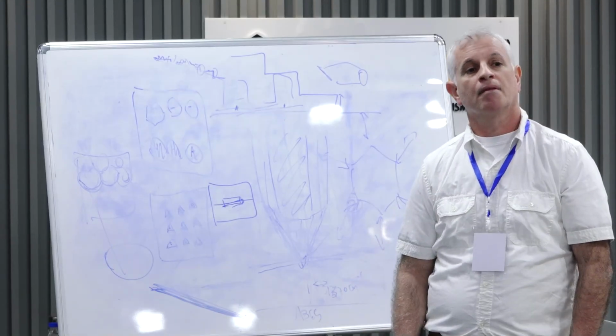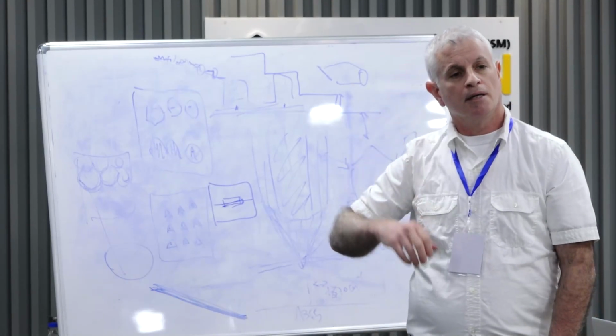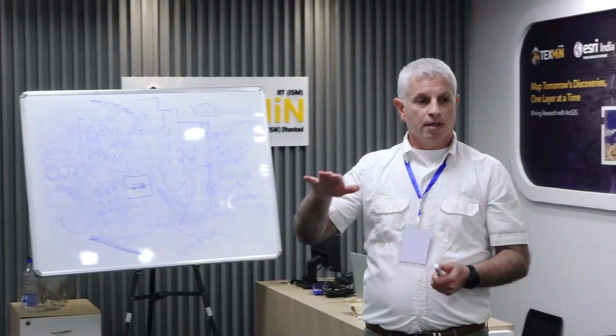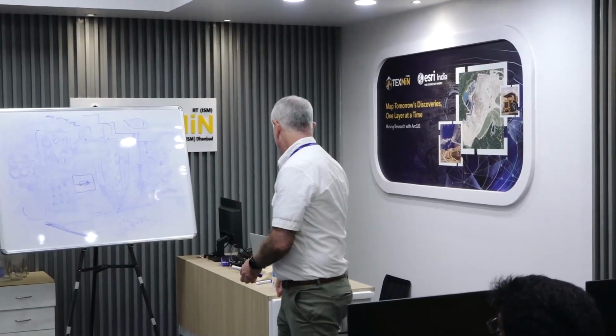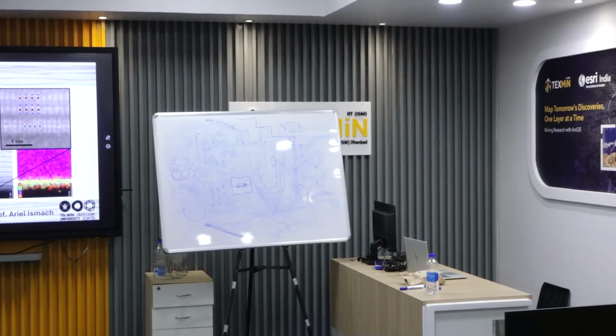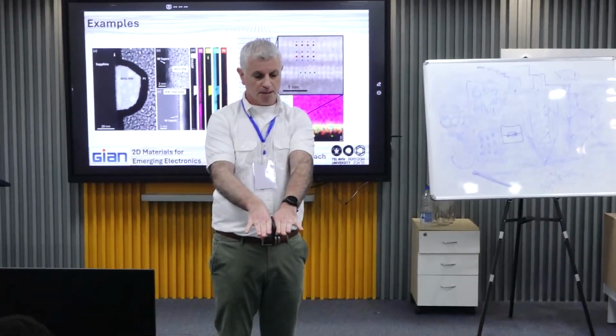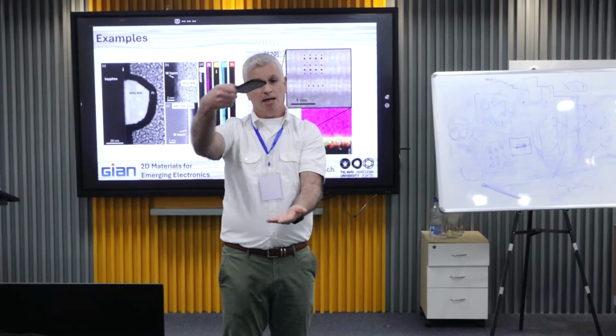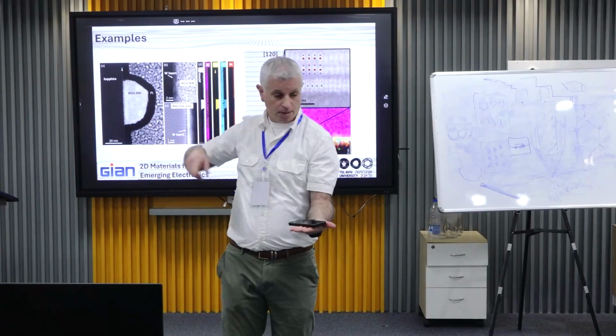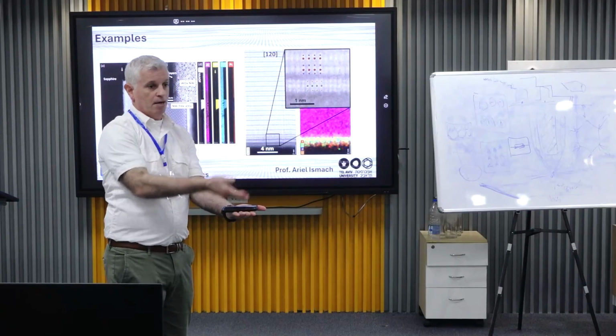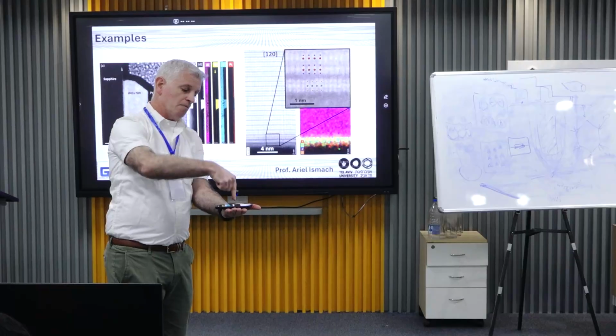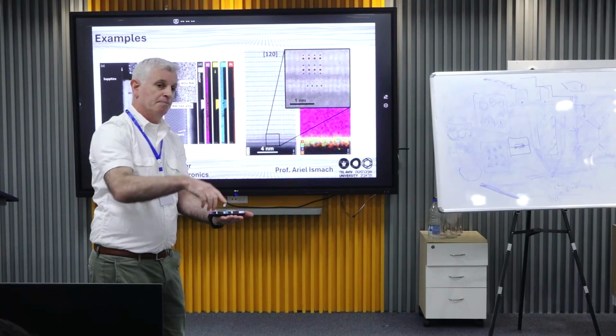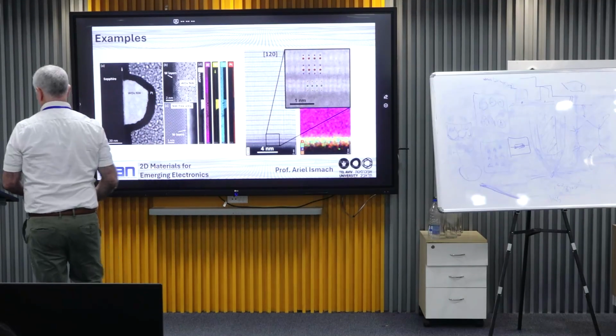So here also pattern transferring only, in the vertical also, like in the horizontal we have a suspended layer, right? Then you take this lamella. Let's say that this is the lamella, and this is the substrate. So I cut and made the lamella, take it out and place it on the TEM grids. So this cross section is now upwards. Then we can come with the TEM, with the electron beam. This is how you make this.